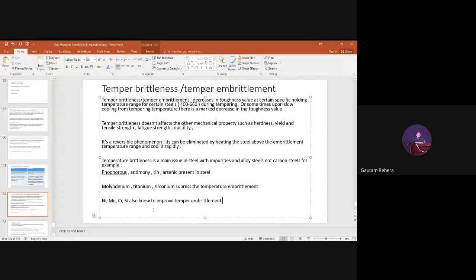If you hold the steel in that temperature range, 400 to 600 or 650 degrees centigrade, that means if you are tempering just after hardening and holding the steel at a temperature of 400 to 650 degrees centigrade, the steel becomes brittle. Instead of softening and an increase in toughness, the toughness will reduce. It becomes brittle. That is called temper brittleness. It also happens when we cool the steel from the tempering temperature at a very slow rate. The exact reason is not understood till now.